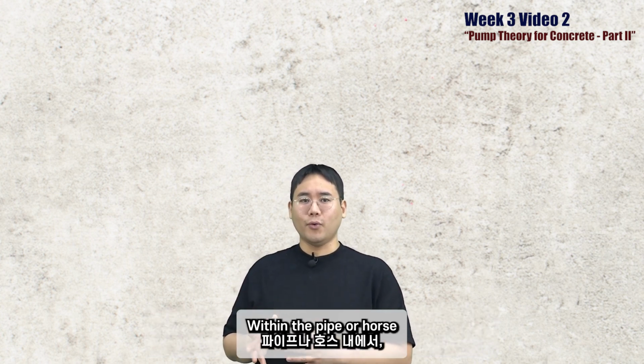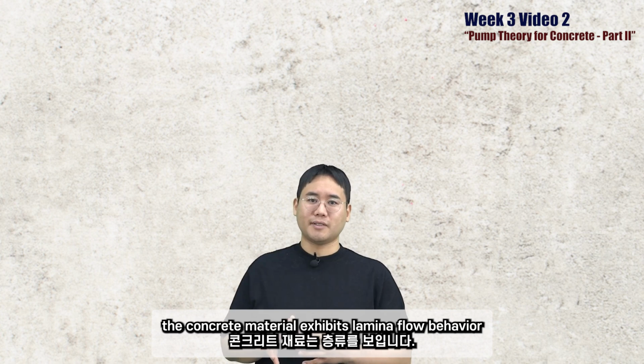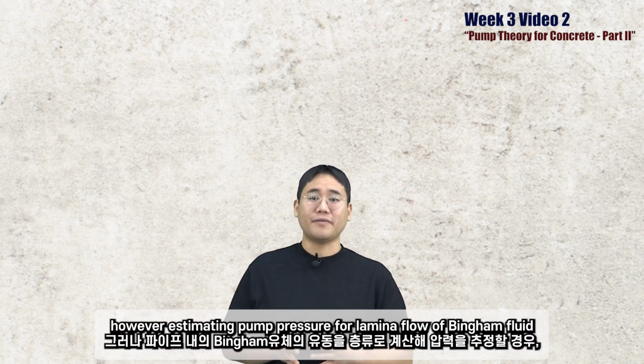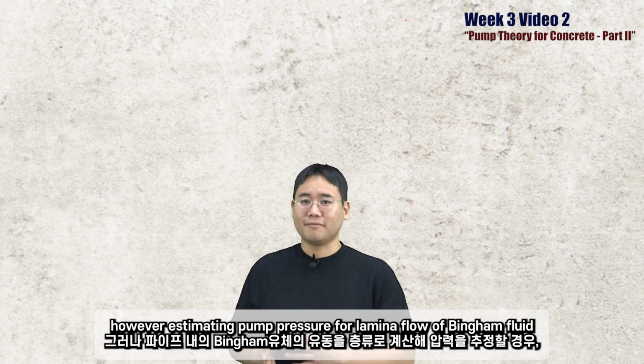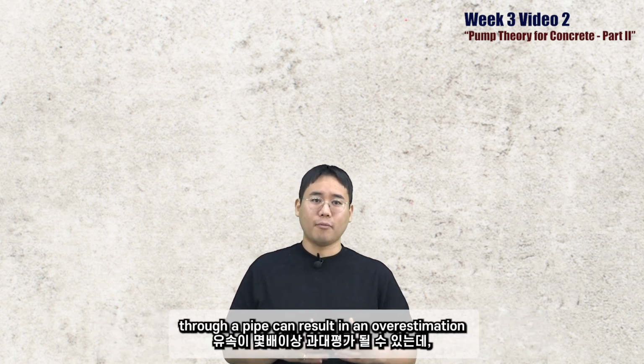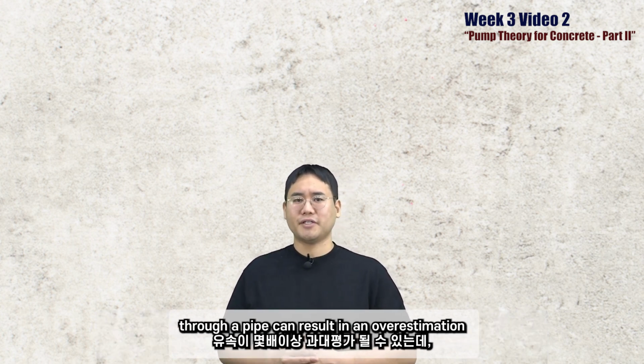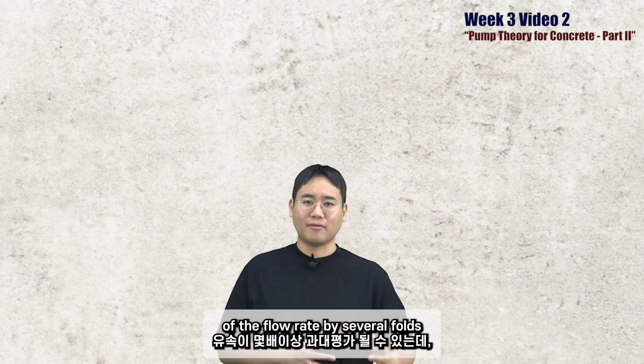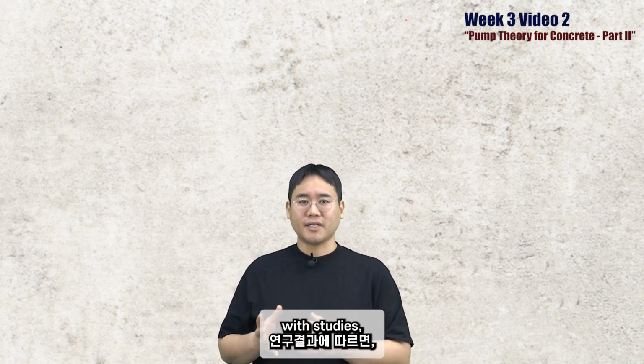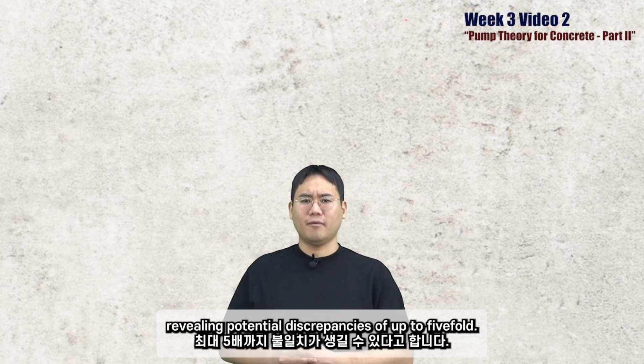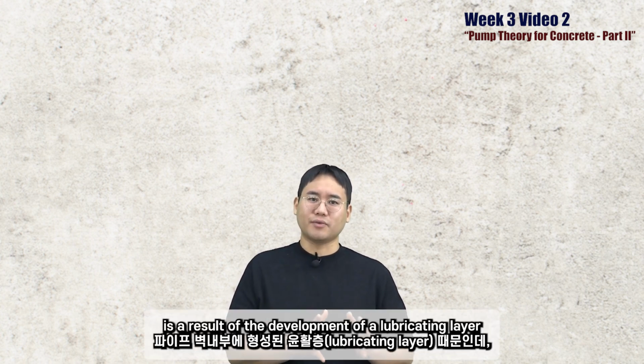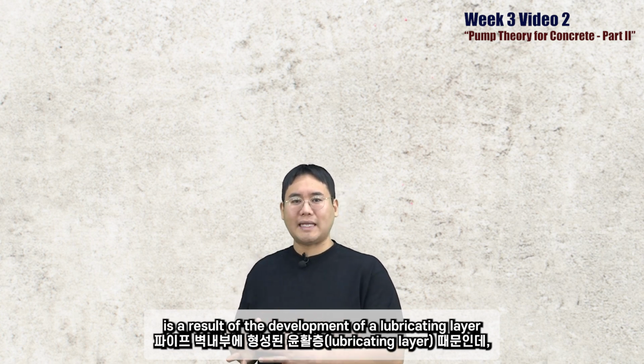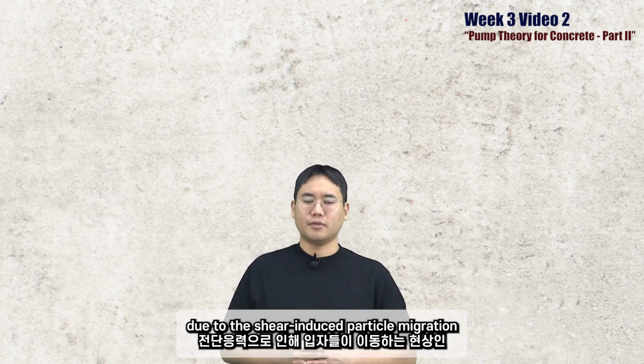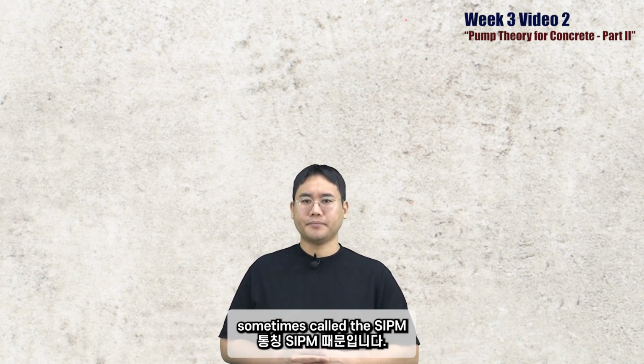Within the pipe or hose, the concrete material exhibits laminar flow behavior. However, estimating pump pressure for laminar flow of a Bingham fluid through a pipe can result in an overestimation of the flow rate by several folds, with studies revealing potential discrepancies of up to 5 folds. This overestimation is a result of the development of a lubricating layer on the pipeline walls due to the shear-induced particle migration, sometimes called SIPM.